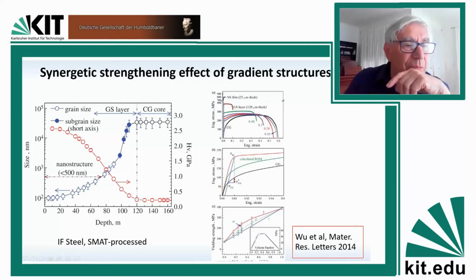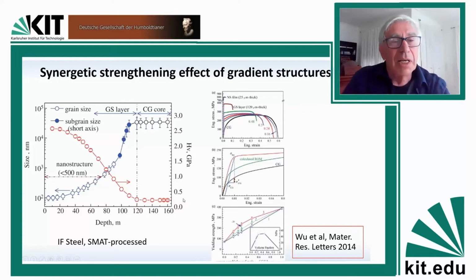For the hard surface one, it is in this range, and then it drops off to a low one in the soft core of the material. Now, if you measure the mechanical properties of layers of materials, if you slice the material like that and have miniaturized specimens and do tensile testing on those specimens, you get the stress strain curve for the coarse-grained material. For the nano-scale material at the surface, it would be a curve like that. And then there are some intermediate ones.